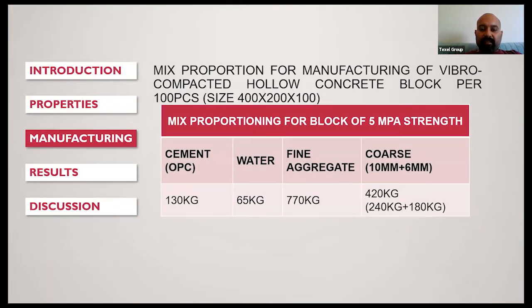I took a mix for hollow concrete blocks of 100 pieces, size 400 by 200 by 100 mm, with cement 130 kg, water 65 kg, plus fine aggregate and coarse aggregate.